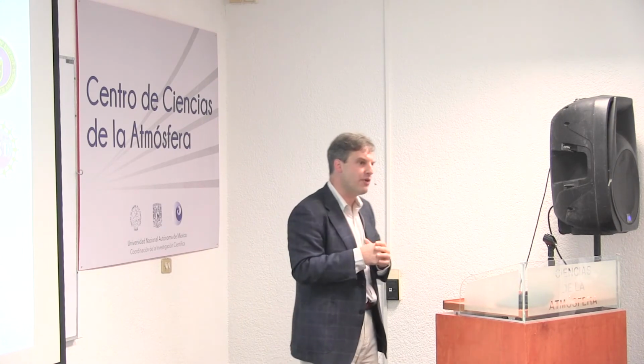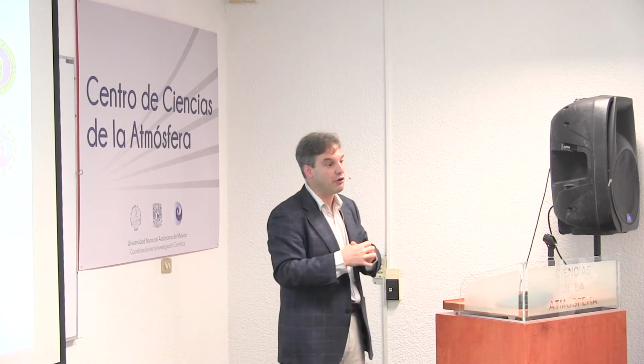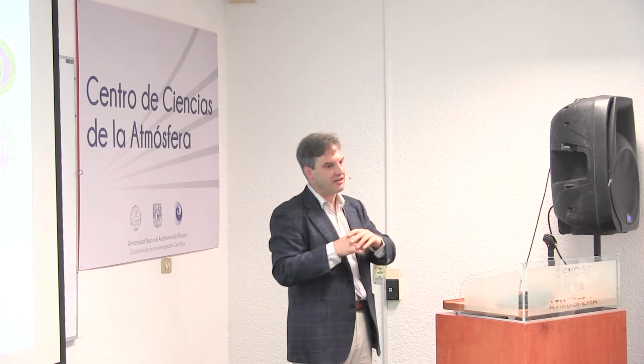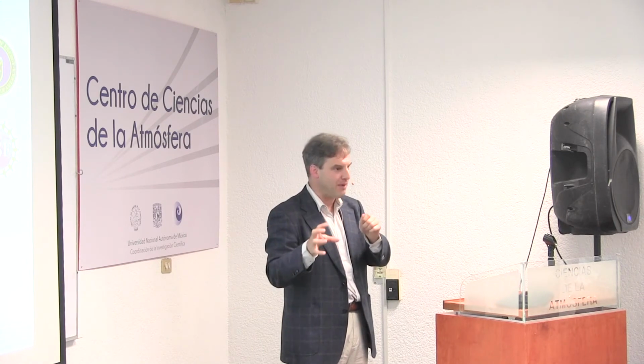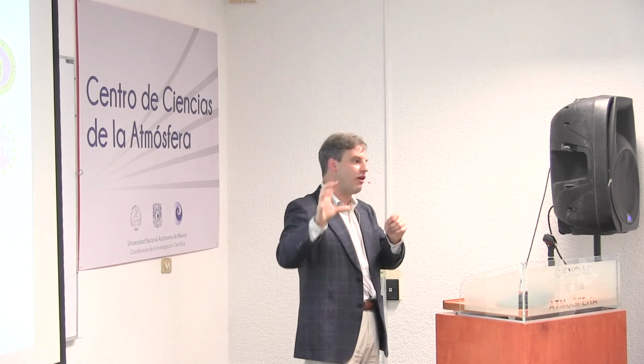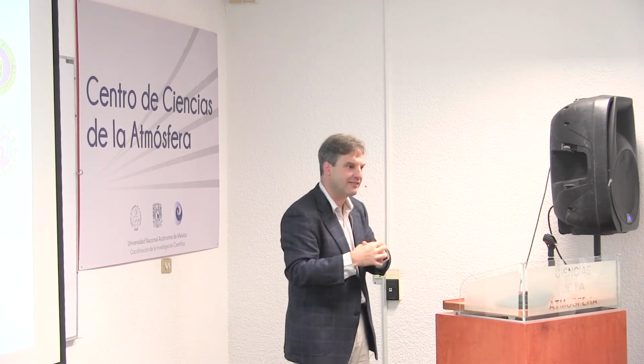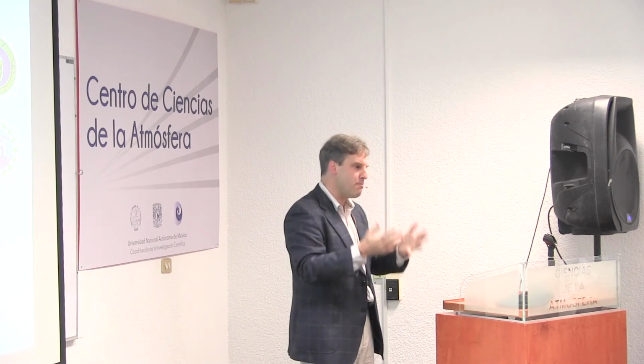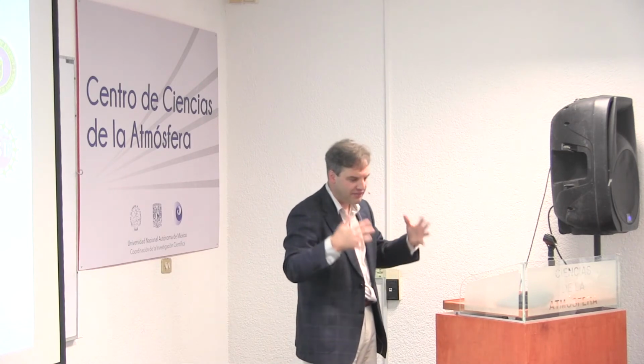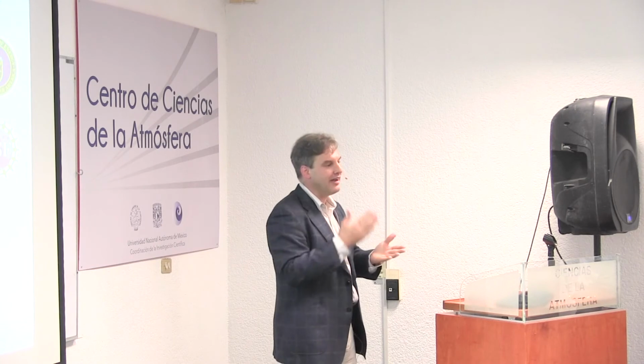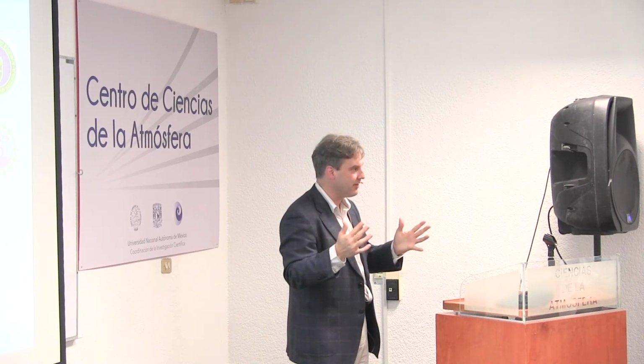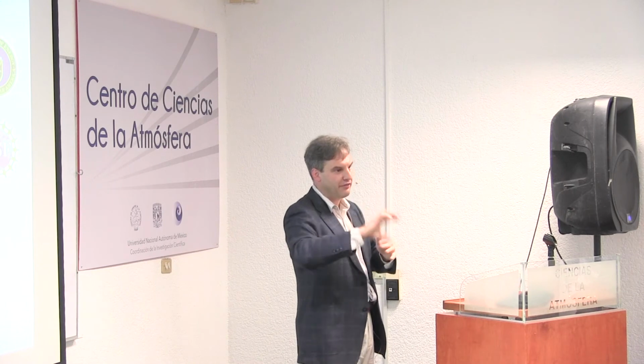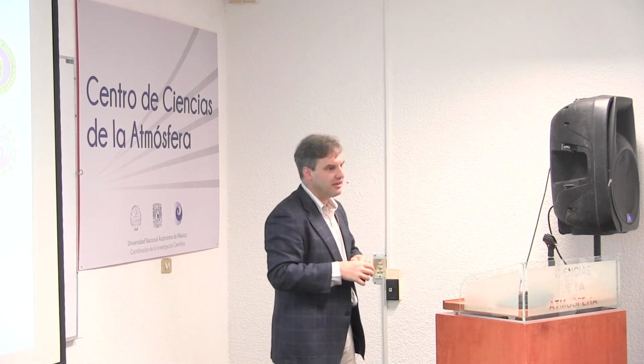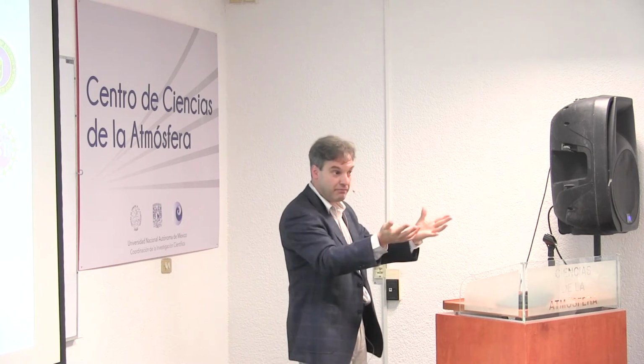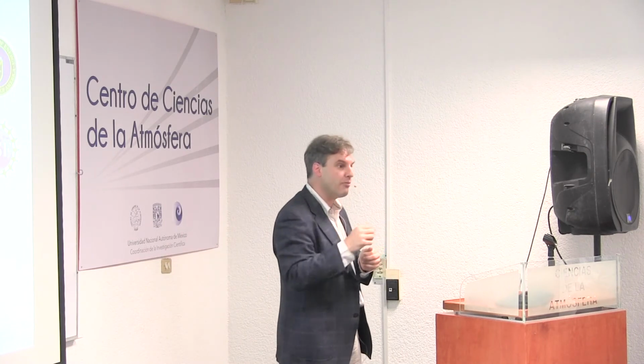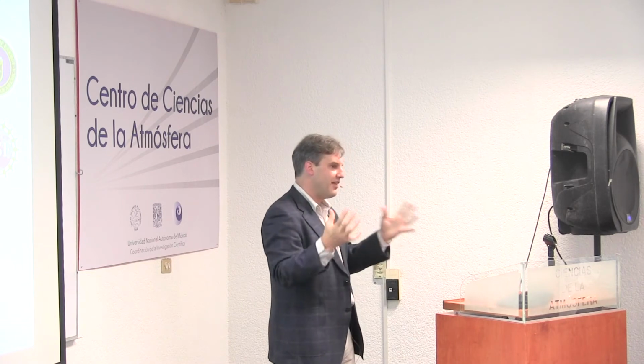There is some knowledge, but that's really the challenge. We had one system where we used naphthalene and made SOA out of it, and the model would not get the glass transition point of the actual particles right, because the model doesn't know all the chemical products in the condensed phase. So you see that many people - Neil Donahue, Shiraiwa and others - if they have high resolution data, try to really nail down the major components because they will affect the glass transition or phase mostly. Maybe it's not completely resolvable because you have millions of species, but this Nature Communications paper gives a good summary, because they had exactly this problem.